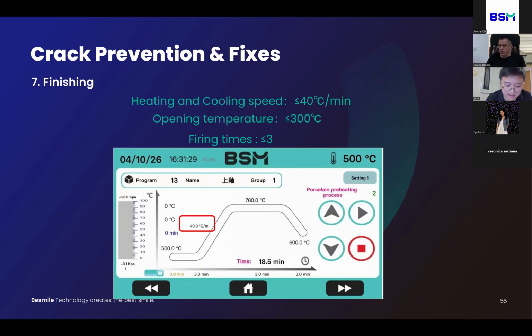And sometimes the technician needs to do several times of firing, several times of sintering. One for veneering and one for glazing, or maybe one for staining. But with the increasing of the firing times, the risk of fracture, the risk of crack will also increase. So we suggest for long bridges, no more than 3 times of firing for the same bridge.